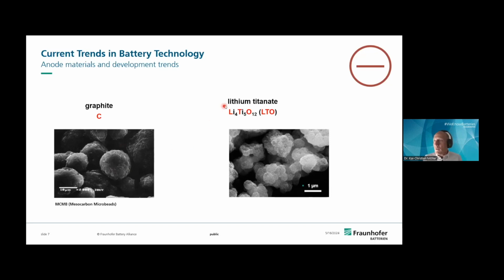A little bit different looks the lithium titanate. It's a nanomaterial. It's in the electrochemical stability window of the electrolyte. So it has a high surface area and small particle diameters. This means the diffusion of the lithium ions in the particle and out is very short, and the battery can react very fast and give high power. A little bit different compared to the carbon.